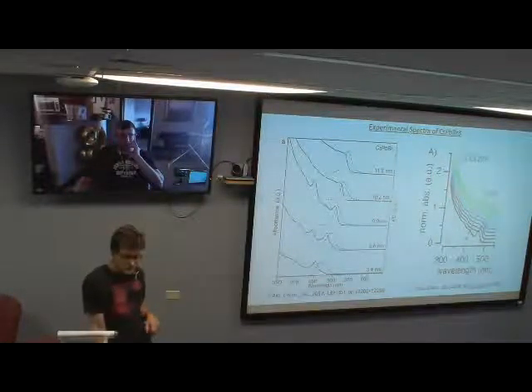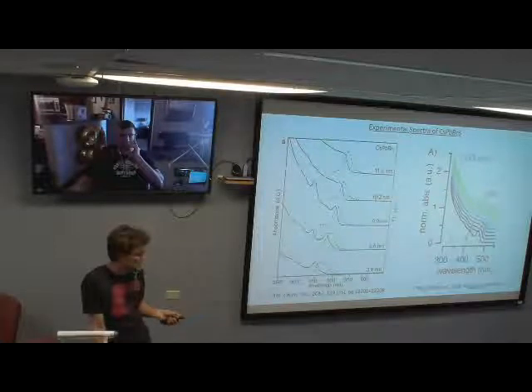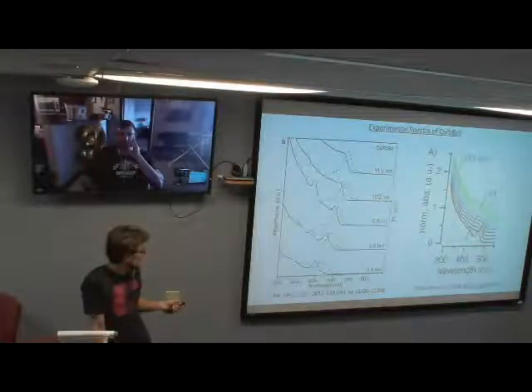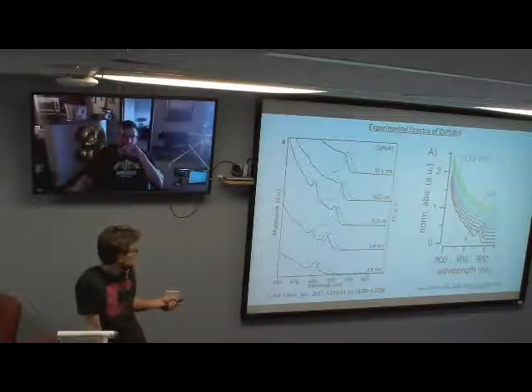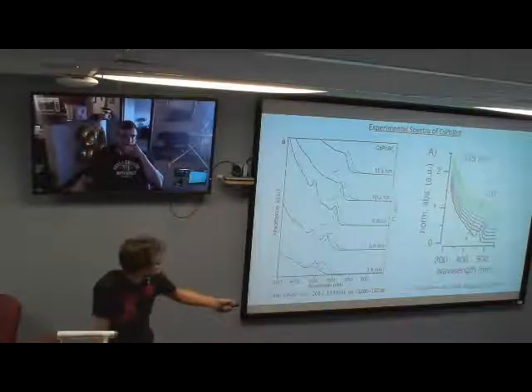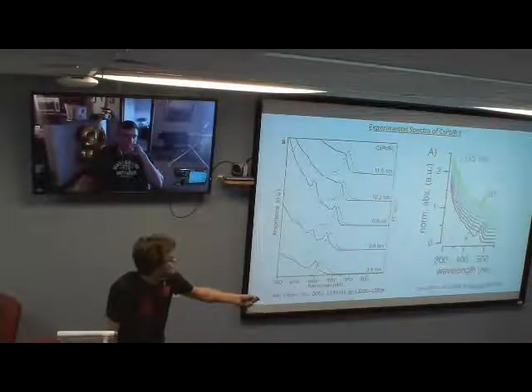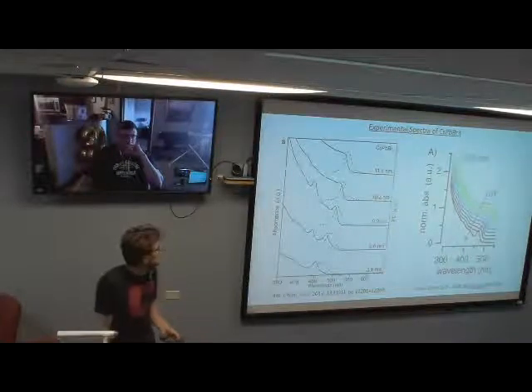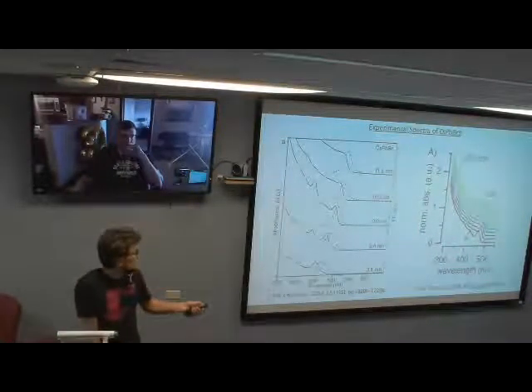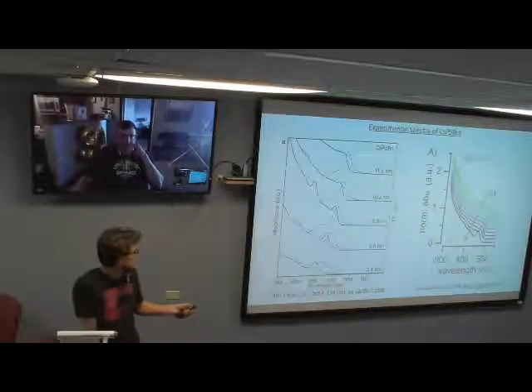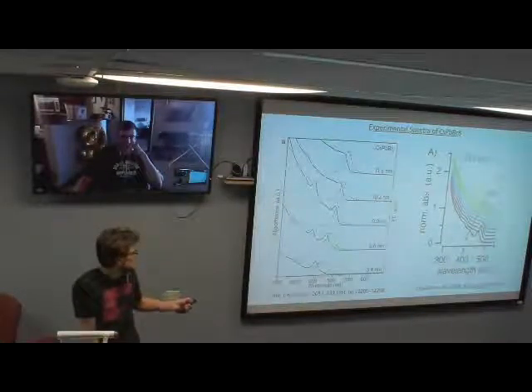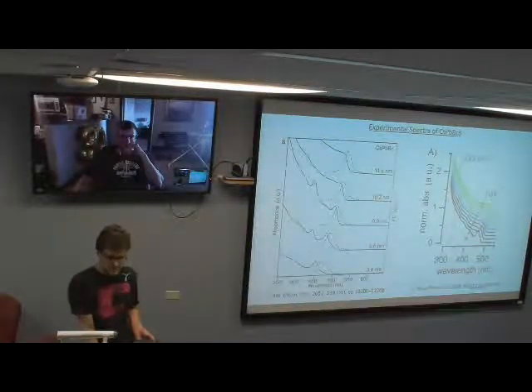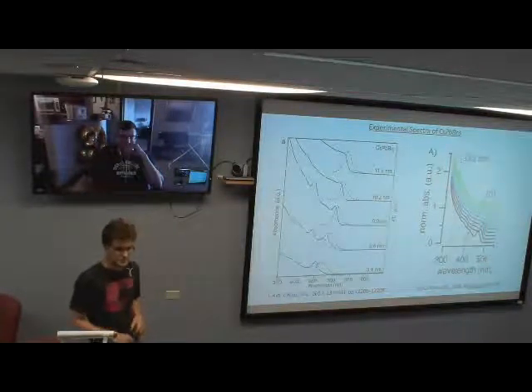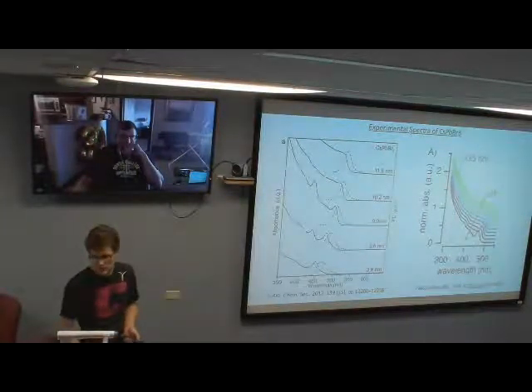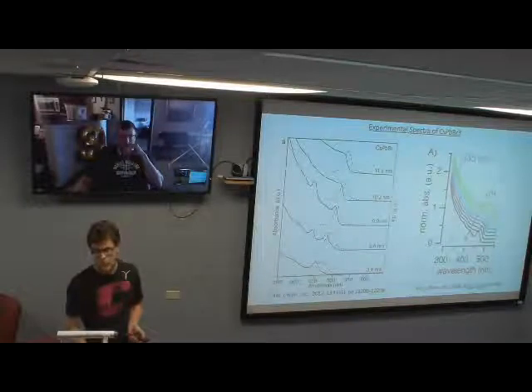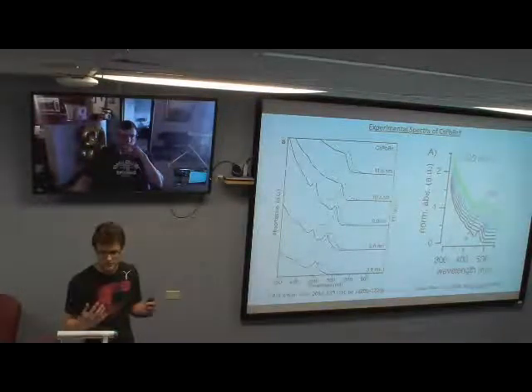So what again, your quantum dot size? 1.5. So it'd be twice less. Yeah, so we expect more comparisons to something like this, or the bottom one over here, although I'm not sure what size that is. Basically, you should see more blue shifting, and you should see more distinct peaks near the band edge. As you become more quantized, you should see it, because of the S and P harmonics of the wave function. Yeah, they'll be more overlap, so they'll be more enhanced.